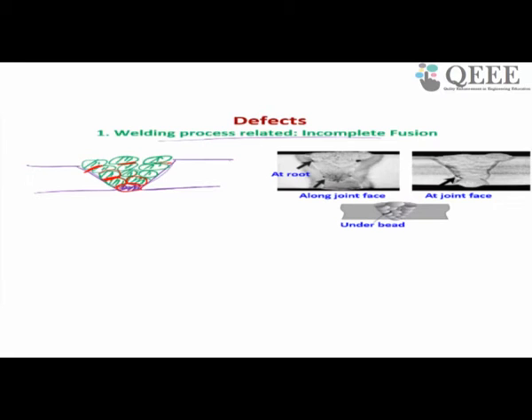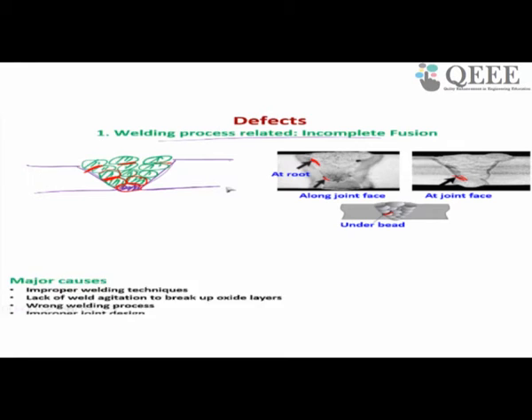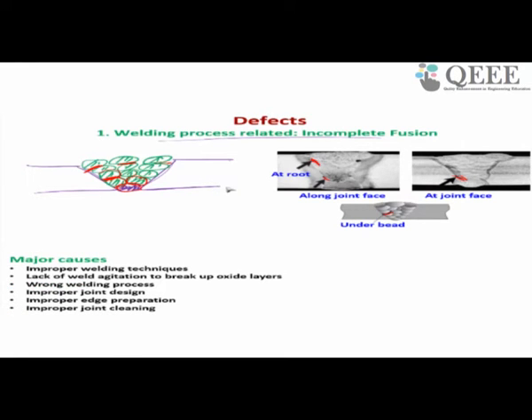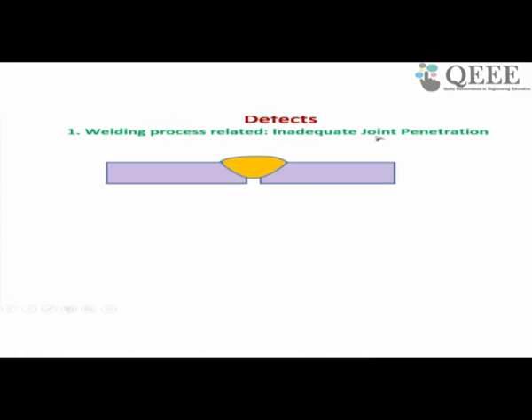It may happen at the face, it may happen inside the bead, and here also it may happen. It may also happen at the root. This is called incomplete fusion. It may happen because of lack of breakup of the oxide layer. As I said, if an oxide layer is there, you have to remove it properly. If some oxide layer is retained, then in that region fusion will not happen. So because of all these reasons you may get this kind of incomplete fusion.